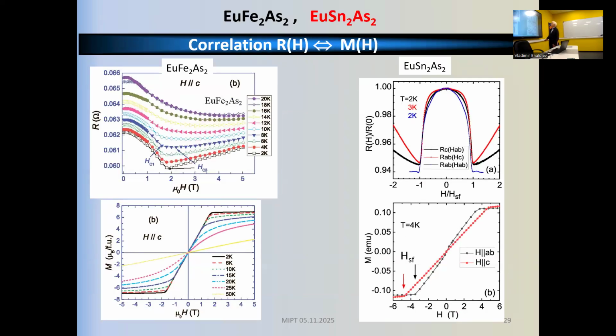Specifically for what we studied here, for europium iron arsenide, EuFe2As2, it develops exactly in a similar way, correlated with the magnetization. As you increase magnetic field, you saturate europium ions, and immediately the negative magnetic resistance vanishes. And indeed, this material is an easy-plane antiferromagnet, so you rotate.